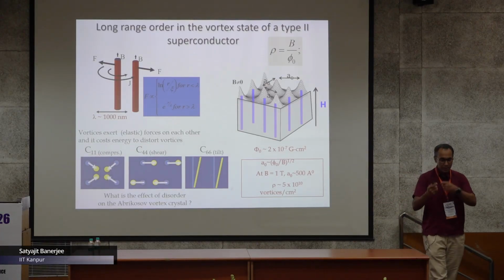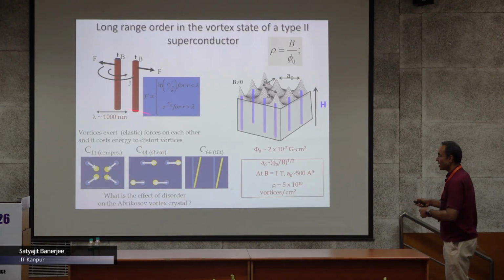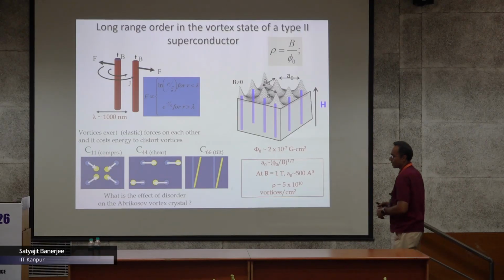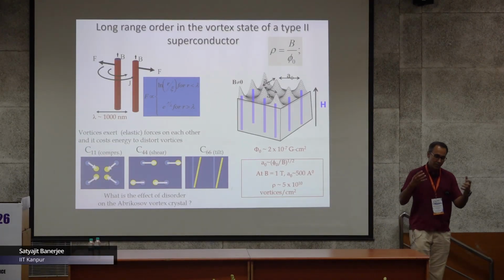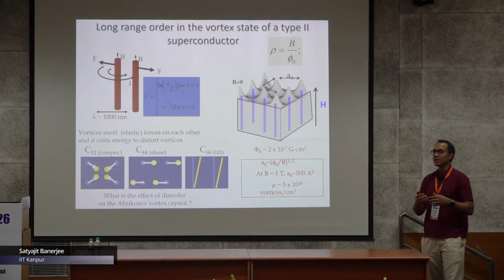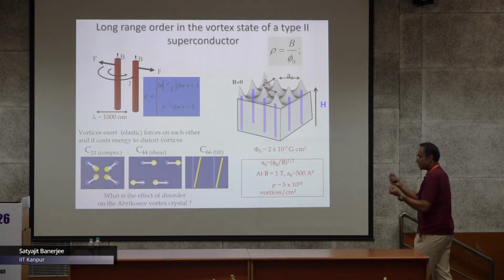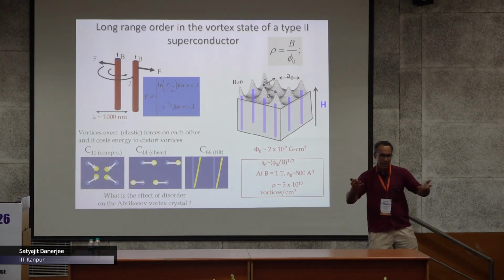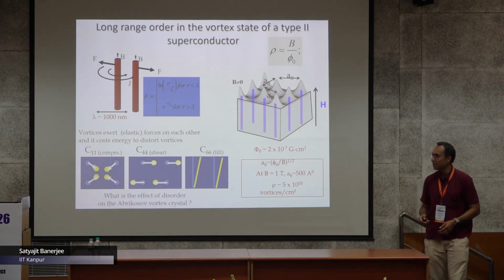It also costs energy to deform or tilt the vortices, so they have an elastic energy associated with them. As I said, the commensurate or incommensurate nature is related to a competition between this elastic energy and the underlying periodic potential that you create inside the system.